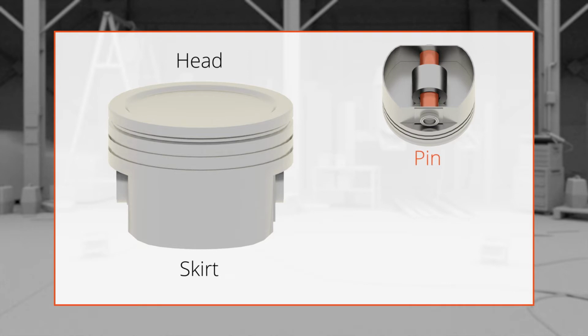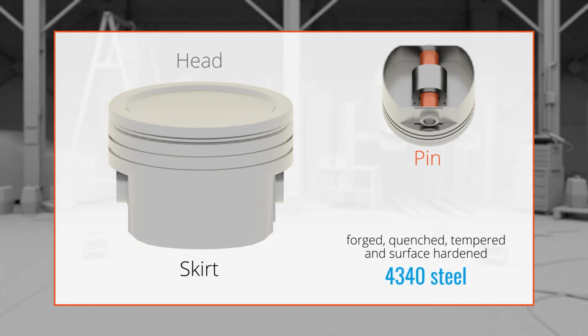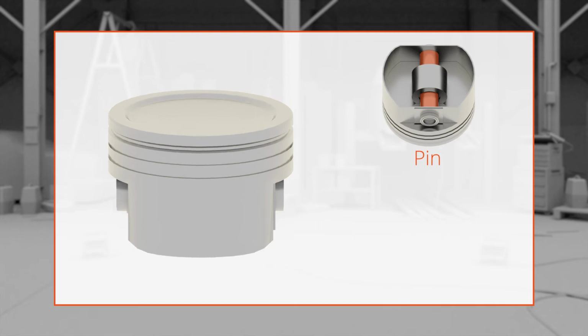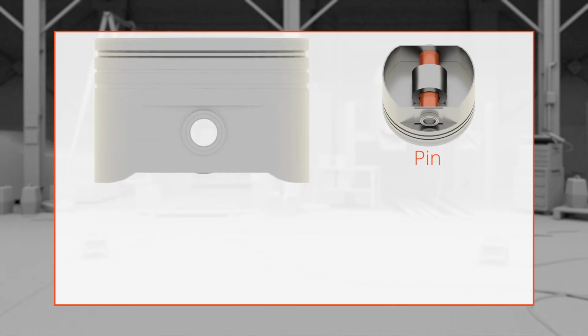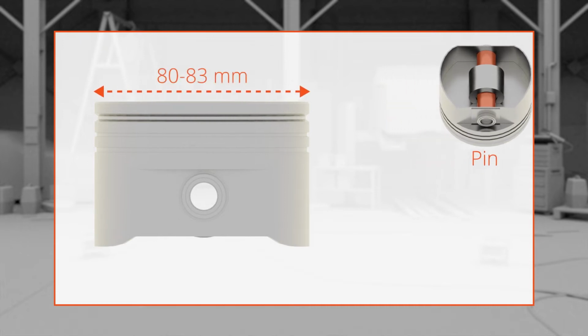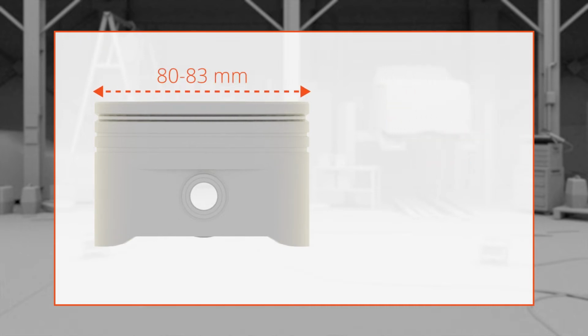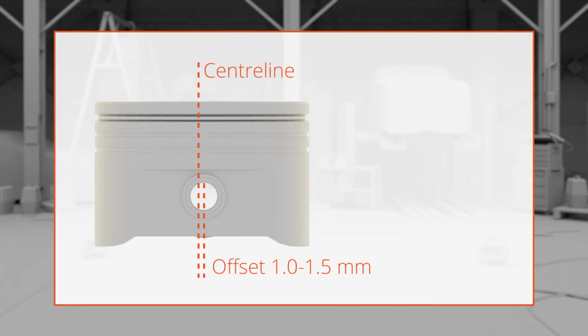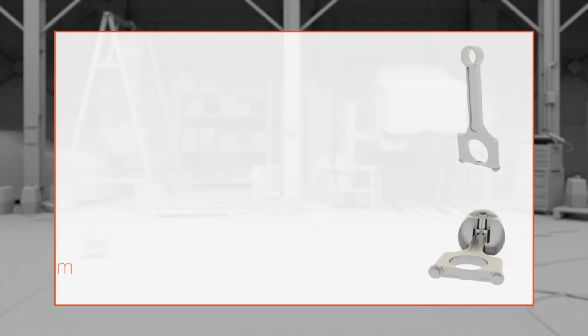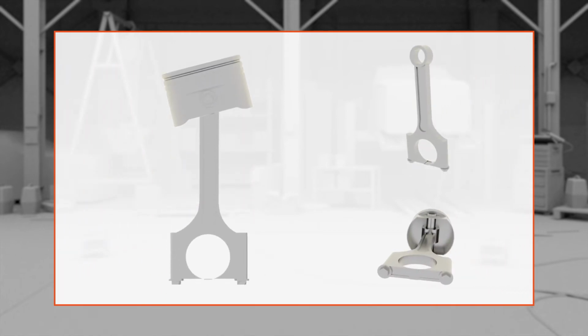Piston pins are typically made from forged, quenched, tempered and surface hardened 4340 steel, which is a chromium, molybdenum and nickel alloyed steel. Surface hardness for abrasion resistance is one of the priorities of piston pins. The piston usually has a diameter of 80 to 83 mm, while the piston pin is offset from dead center usually by 1 to 1.5 mm. The smaller end of the connecting rod attaches to the piston pin, around which it is free to rotate. The resulting friction between the connecting rod and the piston pin is the reason for the specification of surface hardness on the piston pin.